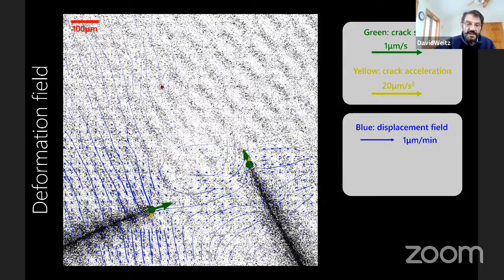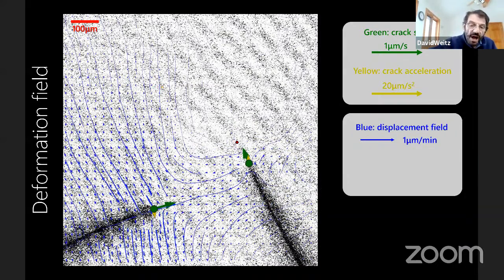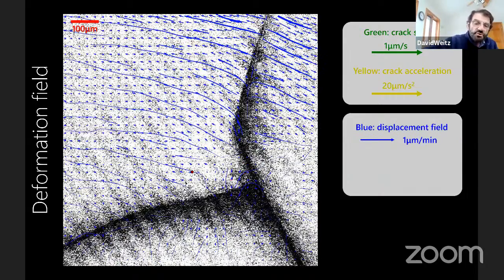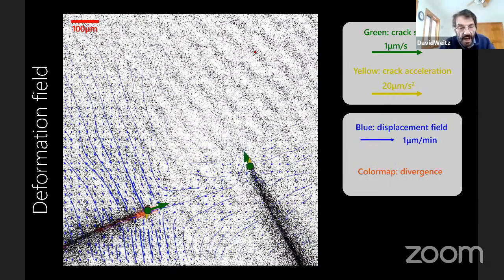The important thing is that the strain field around the crack is really all over. There are large strains far away from the crack, and that's what's driving this large interaction. That's what's driving the fact that this moves off in the direction it does. And then you can see just the divergence of the sample. It's plotted in red. You have the whole strain field of the sample while you're doing it.